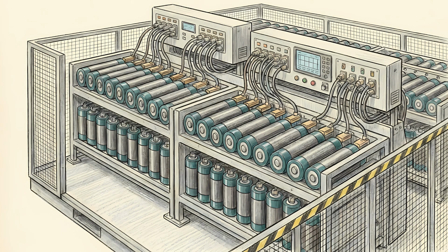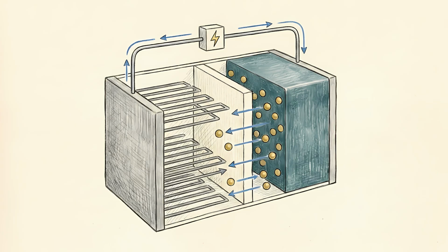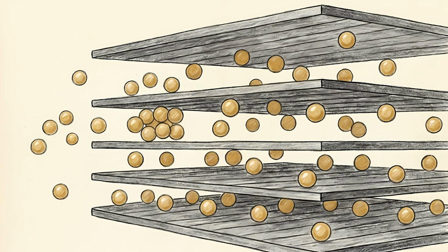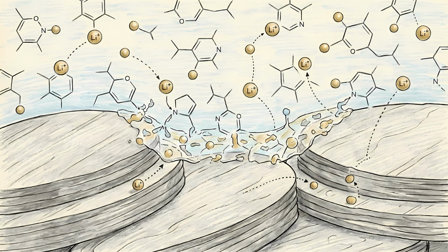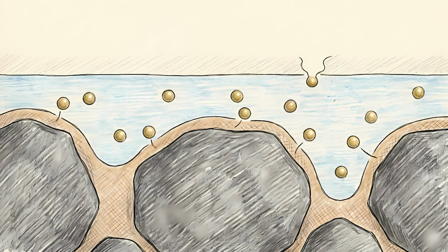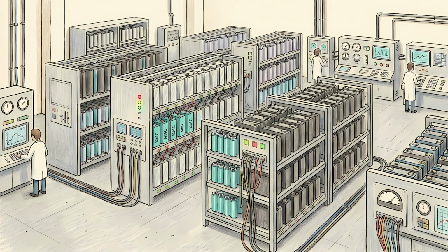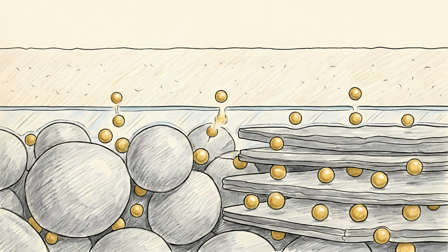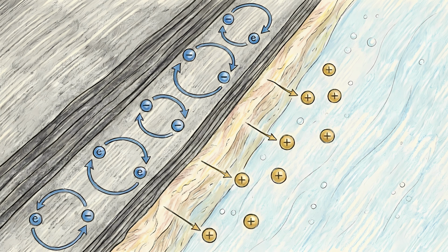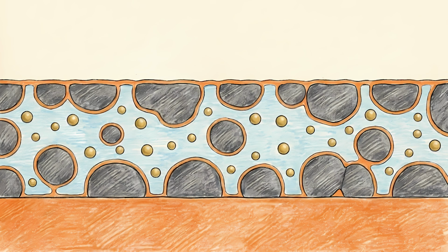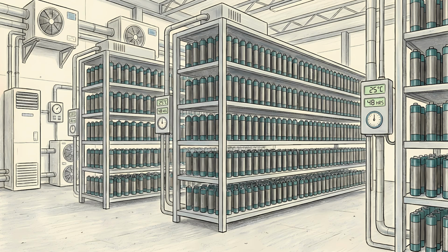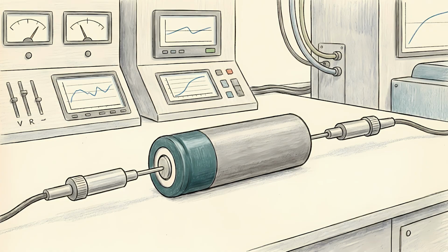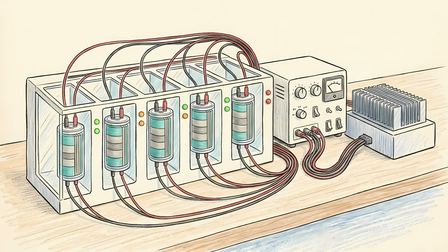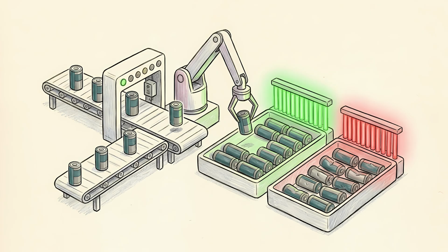It is not. A newly assembled cell must go through formation, its first carefully controlled charging and discharging steps. The first charge moves lithium from the positive material toward the graphite. At the graphite surface, some electrolyte reacts and forms a protective layer called the solid electrolyte interface, or SEI. A useful SEI limits further electrolyte decomposition while allowing lithium ions to pass. Its quality affects resistance, lifetime, and safety. So the cell spends its first hours moving slowly through the factory's tutorial level. It is formed, rested, measured, and tested before anyone trusts it.